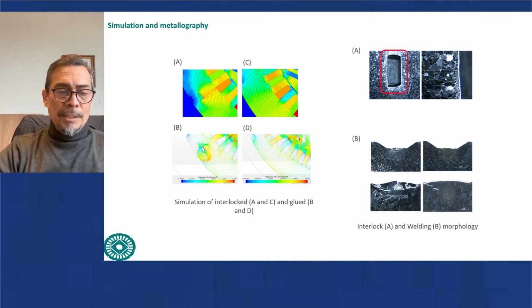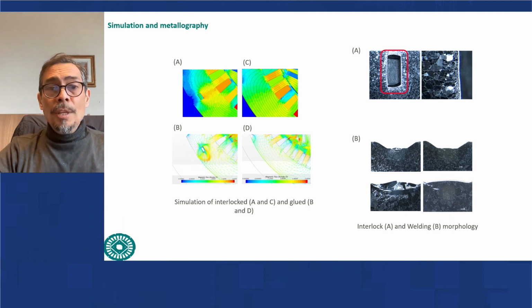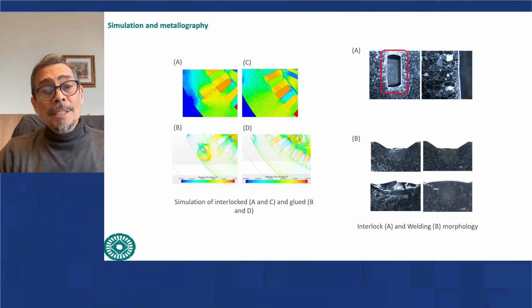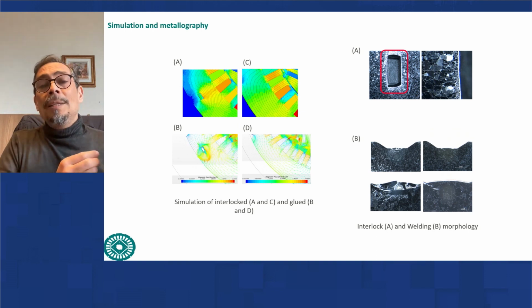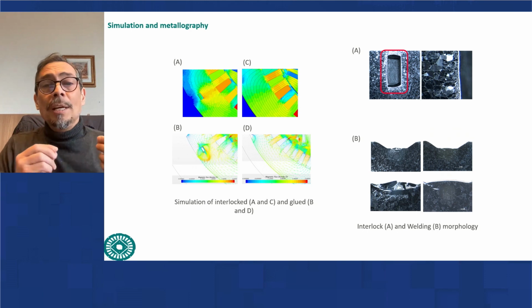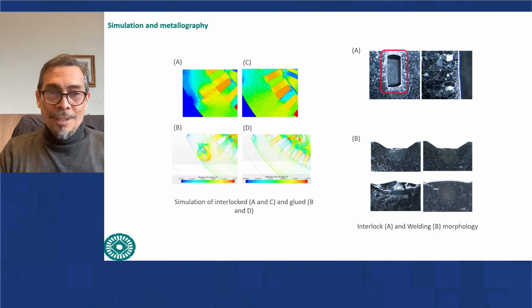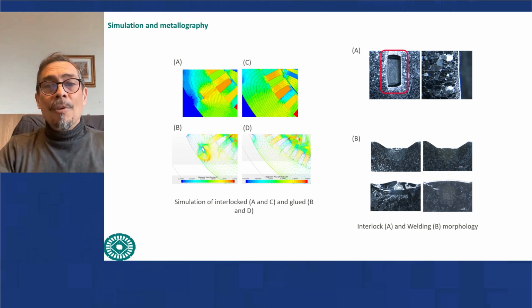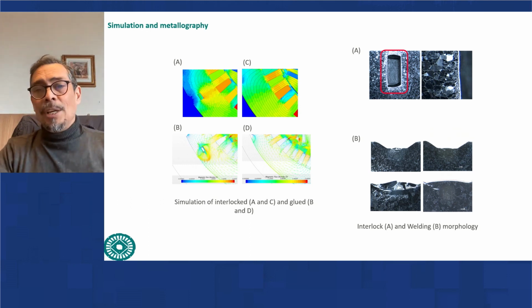These losses come basically from the damage that is made by these conventional methods on the special alloys that are produced by our steel mills. And this is very important to understand because the steel mills invest a great amount of carbon footprint in producing a very sophisticated alloy. Our message is: try not to damage that special lamination because we have invested so much carbon footprint in it. So let's avoid breaking it, making holes in it, welding it, let's say overheating it.